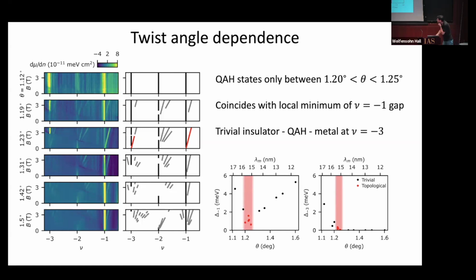At 1.5 degrees twist, there you seem to have a feature that looks like a quantum anomalous Hall thing. It's not super prominent. So you think this is something sloped? Is that right? You're picking that out by eye? Yeah. So if you look closely, this color scale is probably not ideal for showing this. If you look closely, what you should believe is that up to about a half a Tesla, I think a few tenths of Tesla at least, it's actually vertical if you look carefully enough at low magnetic field. And then you get states which are coming out which look like they are sloped.